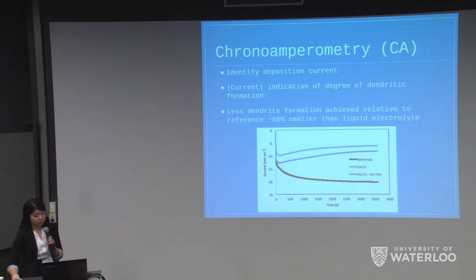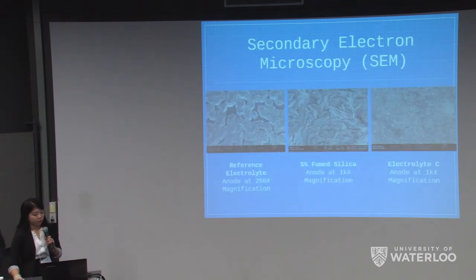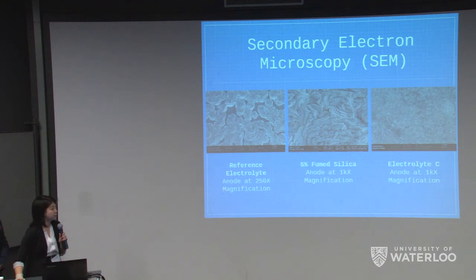But even with these results, the CA test is not enough to determine whether or not there's formation, because there is also the orientation and uniformity of the dendritic deposition, as I mentioned earlier. Thus, we had to use SEM in conjunction to allow a qualitative observation of the dendritic formation. If the deposition results in an even and smooth surface, this means that no or little dendrites have formed on the surface. And if the deposition is uneven or comprises flakes and other types of uneven growth, this means that dendrites have formed and will act to gradually destroy the battery's performance, as it results in a non-equal distribution of the electrolyte and potentially can cause a short circuit.